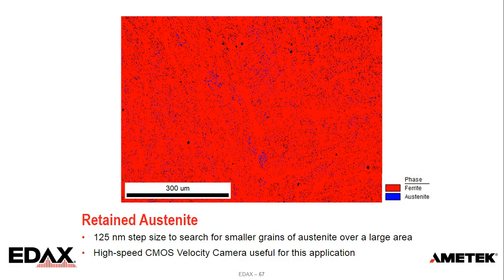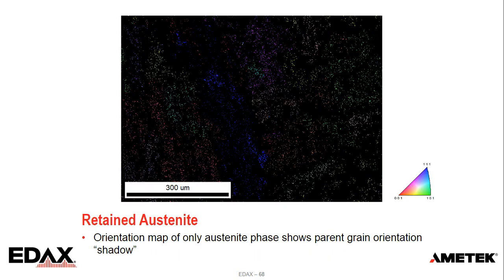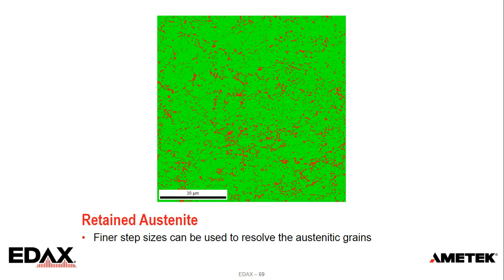What's kind of cool about this is that as we look at an orientation map of just the austenite, you can see the colors, and the black makes it a little hard to see, but you see sort of the shadow or the outline of the parent grain orientation. So this has been used to look at some of the reconstruction as well, to show how it's working and when it's working. So we can measure retained austenite with EBSD. And of course, as we go to finer and finer step sizes, we can resolve more and more of those grains. So it becomes a sampling statistic, an approach of how to best do that.